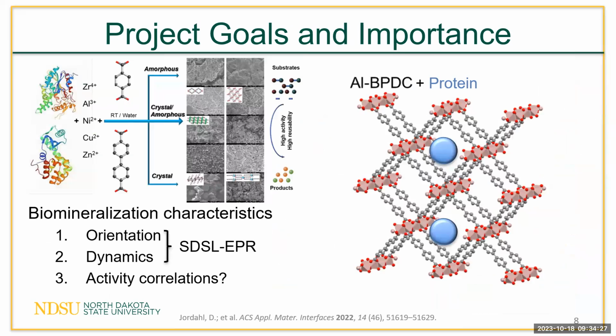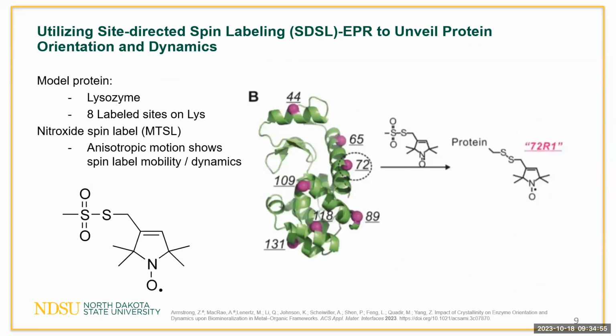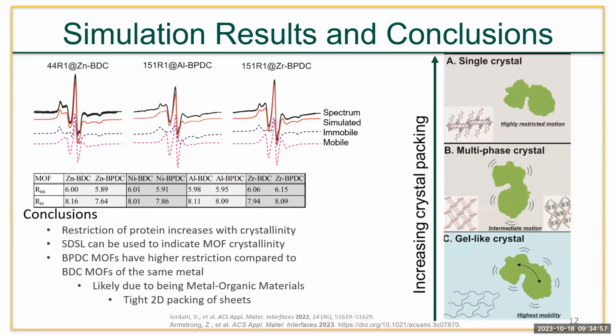And then on top of that, when we did do BET in the previous publication in 2022, we didn't find these materials to have great high specific surface area. And we attributed this to potentially pores collapsing because of the less crystallinity and maybe less stable materials when we dry them out for BET analysis, or maybe since we also thought that they could be 2D sheets for some of these materials. Let me see if I have a picture of it here.